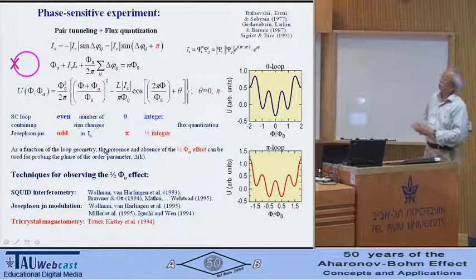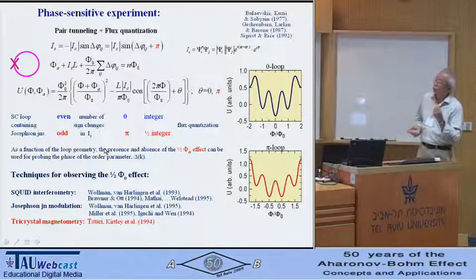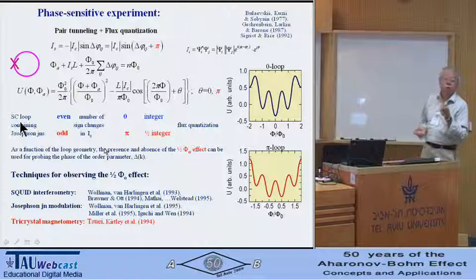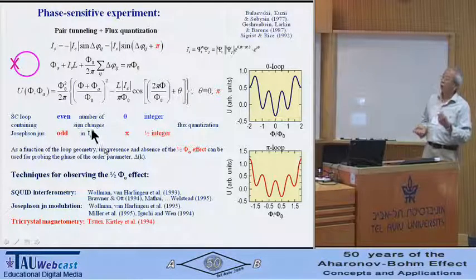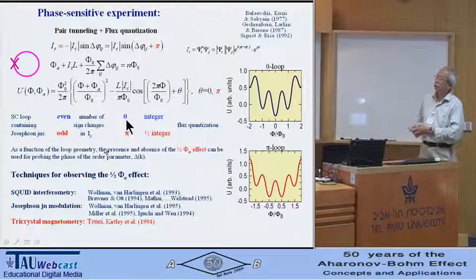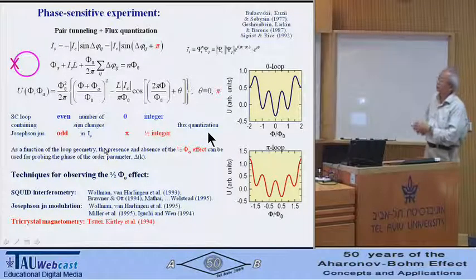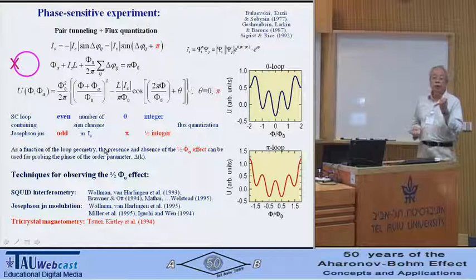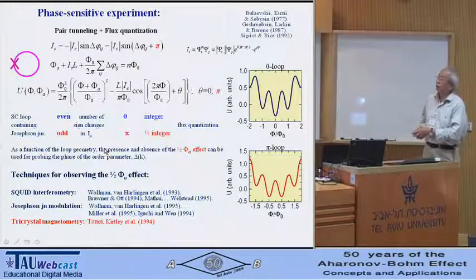So when you calculate the energy for a superconducting loop containing Josephson junctions, all you have to do is count the number of sign changes in the supercurrent. If it's an even number of sign changes, then you get a net phase of 0 or 2 pi, and that leads to regular integer flux quantization, as I indicated here. Now, if the number of sign changes is odd, then you get a net phase change of pi.